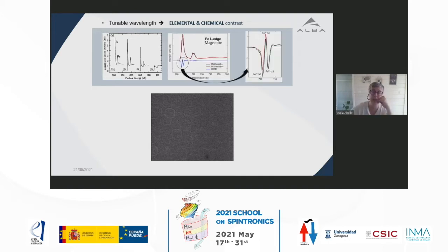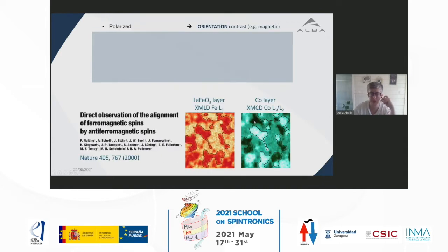Not only different elements, but in some favorable cases, one can look even at different, for example, oxidation states, or in the case that I will show here, one can look at different cations within a complex oxide structure. Each one has a particular peak, and one can look at the magnetization of each one of those subspecies, or cation sites. And this is just a little example, not to make the talk so boring, which is images of a magnetite surface. This is a spectrum of magnetite. As we go through the different dichroic peaks, 1, 2, 3, you will see the magnetization invert and then change and then go on. These are the so-called L3 and L2 absorption edges, and each one has the characteristic dichroic signal that I think Adriana introduced the other day a little bit.